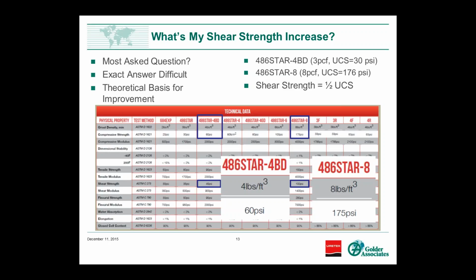So in the ground, when you have a little more confinement, the density is actually going to be higher. If you pull a sample out of the ground and test it, it's going to be a higher density than that. But from what I understand, it's probably in the neighborhood of 20 pounds per cubic foot.